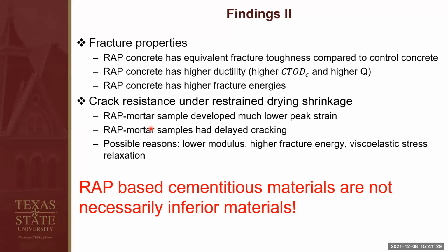The possible reasons for the better cracking resistance are the lower modulus of the material by adding RAP, and also the higher fracture energies, which we already proved in our fracture tests. We also think the stress relaxation due to the higher viscoelasticity of the material can also be a significant source for the improved cracking resistance. So based on these conclusions, RAP-based cementitious materials are not necessarily inferior materials. That's our conclusion.